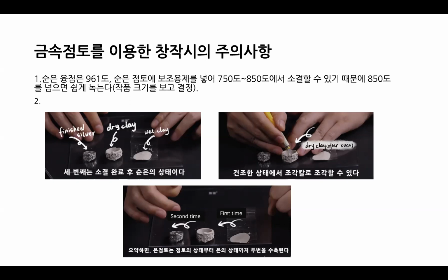The second point is the introduction of the clay states. On the far right of picture 1 is clay in a wet state, which can be shaped at this time. The middle one is dry clay. In the dry state, we can carve it. The left one is the finished product, which can be polished. From the state of mud to the state of the finished one, the silver clay will contract twice with a shrink rate of about 10%.